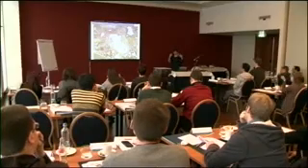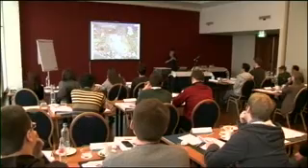So, you know, small grains may be a relatively low weight fraction, but they've got a very high surface, and the reaction all happens by dissolution at the surface. So in this final microstructure, the most important part is this outer product here. And you see this has got rather a complex microstructure, with areas of CSH, little pores in it.